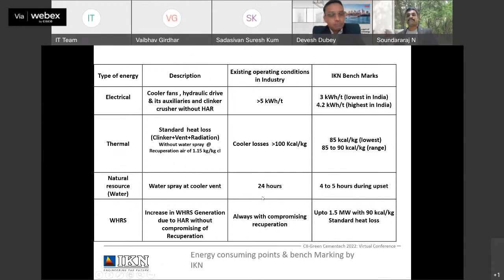In the IKN, we have set a benchmark in power consumption, against more than 5 units, with our lowest number in India operating at 3 units and highest number operating at 4.2. So there is an average difference of 1.5 to 2 units compared to the existing operating conditions in the other coolers in the industry. Thermal energy also, similarly, we have a 15 kilocalorie difference, and in the natural resources of water, we are using only 4 to 5 hours in a day, only during upset conditions.